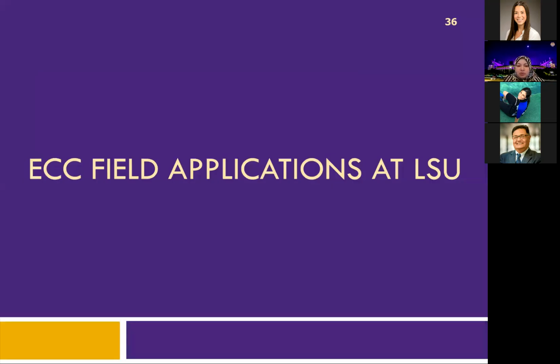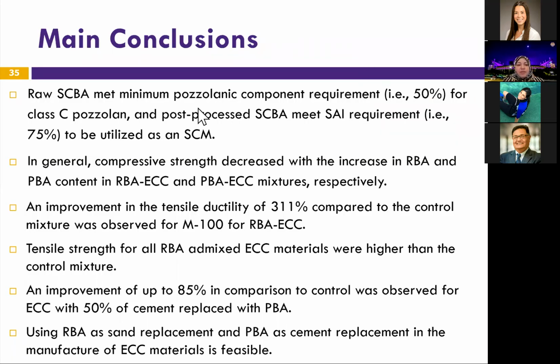So, some conclusions. The most interesting part is that the raw bagasse ash and the processed bagasse ash both met ASTM standards to be used as a pozzolanic material. In general, compressive strength decreased with the increase in raw bagasse ash and processed bagasse ash. An improvement in the tensile ductility of 311% compared to control was observed in some of the mixes. The tensile strengths for all raw bagasse ash admixtures were higher than the control.